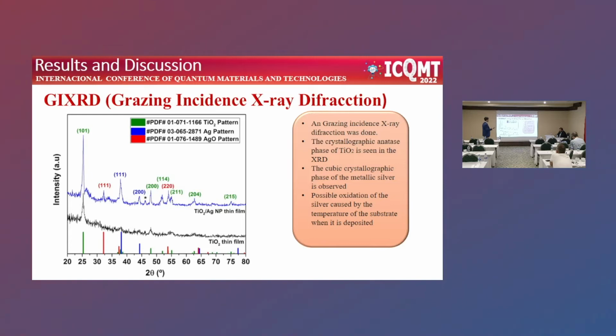Well, using the grazing incidence X-ray diffraction, grazing incidence is the diffraction that we use when you are working with thin films. If you work with powder, you only use X-ray diffraction. When we use grazing incidence X-ray diffraction, we can see perfectly the peaks of the silver pattern, and of course the peaks related to the anatase phase of the titanium oxide. As we can see, there are also peaks of silver oxide. Well, it's normal because we produce heating in the nanoparticles, and the nanoparticles are not really stable with this type of process. So it's normal to obtain this because of the temperatures. It's not a problem because the photocatalytic property hasn't changed with a little bit of oxidation of the silver nanoparticles.